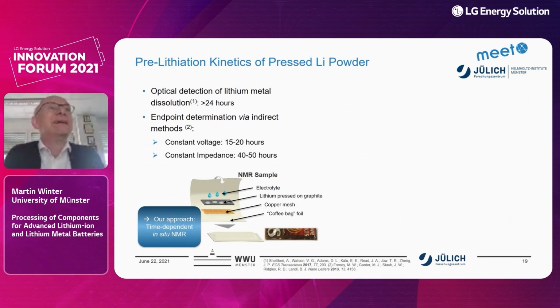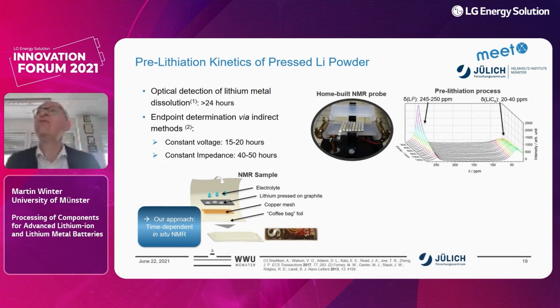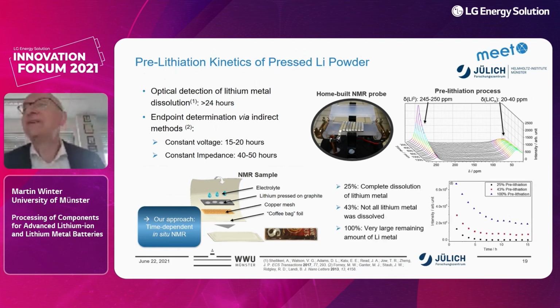Our approach is time-dependent in situ NMR. So we are looking at the lithium dissolution over time, and we are looking at the formation of lithiated carbon over time. Here, 1200 minutes, and this is actually an NMR probe that has been built. So it's a kind of in situ, but in situ to time process. And we then took different amounts of lithium metal. We took 25% of lithium metal. Here we have a complete dissolution of lithium metal.